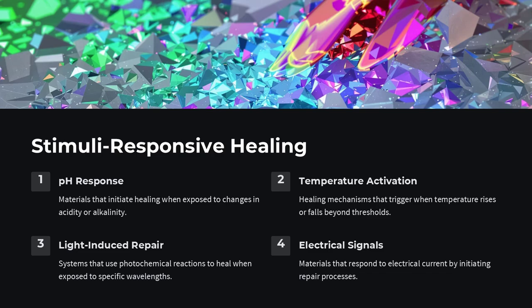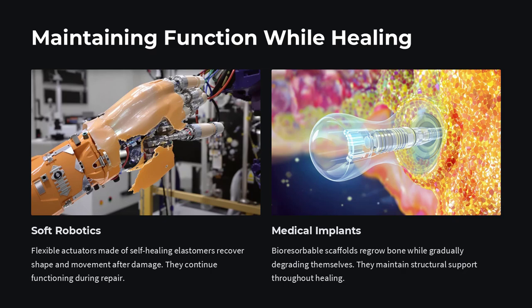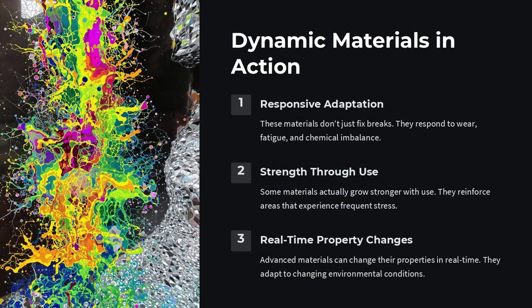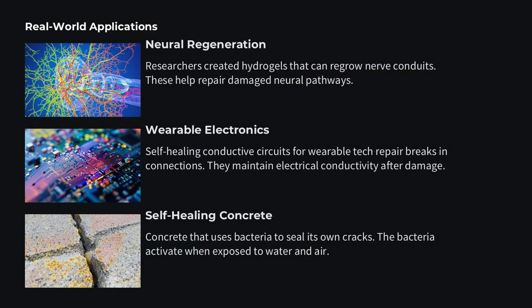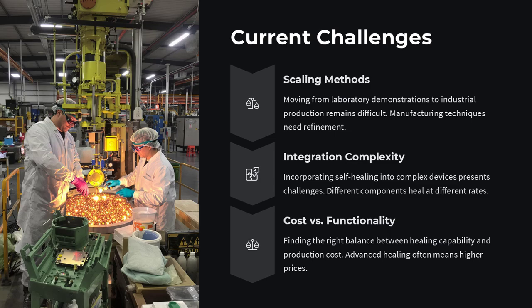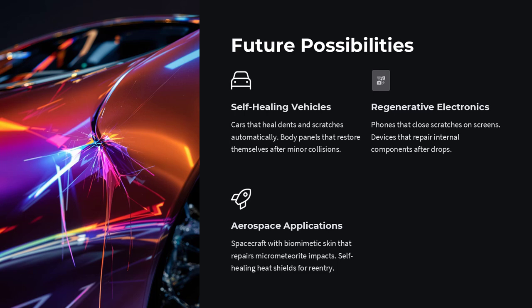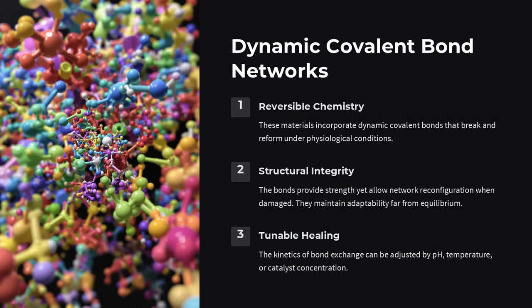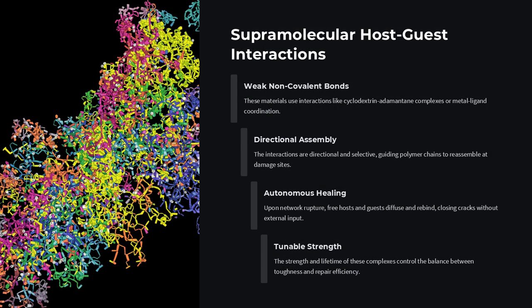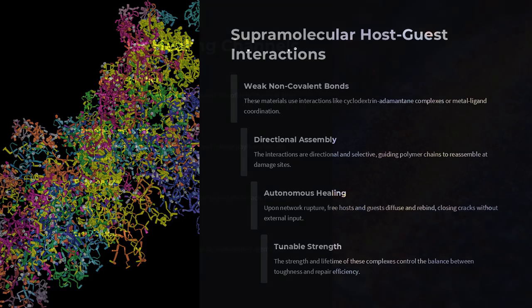So, how do they work? At the core of self-healing lies the idea of non-equilibrium systems, materials that are constantly exchanging energy or matter with their environment, allowing them to stay dynamic rather than static. Traditional materials are at rest once formed, but self-healing ones are designed to reactivate internal chemistry when disturbed. For example, some polymer gels contain microcapsules of reactive agents that, when a crack forms, rupture and flow into the damaged site, where they chemically bond and close the gap. Others use reversible chemical bonds, like hydrogen bonding or metal-ligand coordination, that break under stress and reform when conditions stabilize.